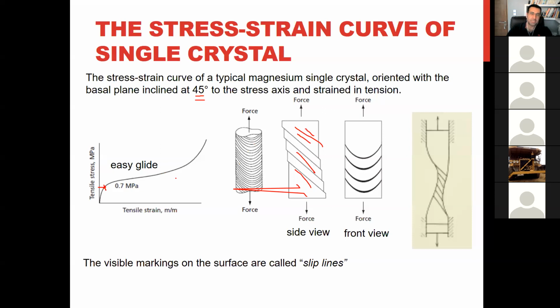And there is no reason, when we reach this critical stress, for further deformation, for an increase of the stress. It means here we have a plateau, so it must be like this, yeah? But actually it's not like this. When we reach here, the sample starts to deform, needing higher tensile strength.